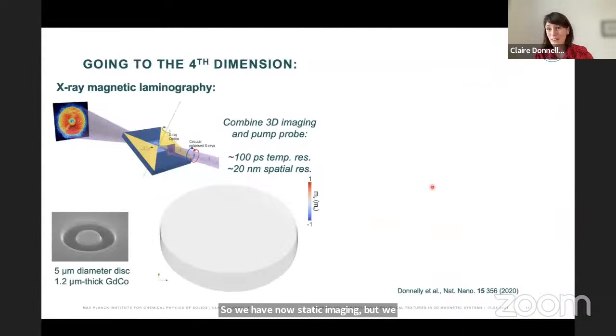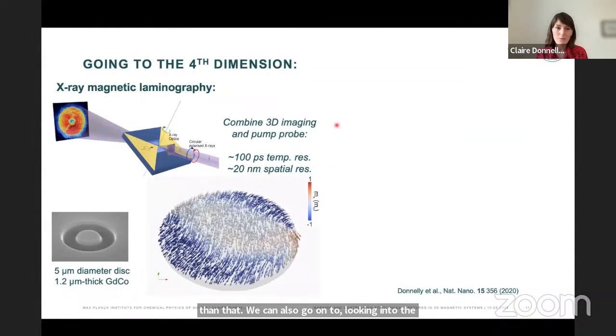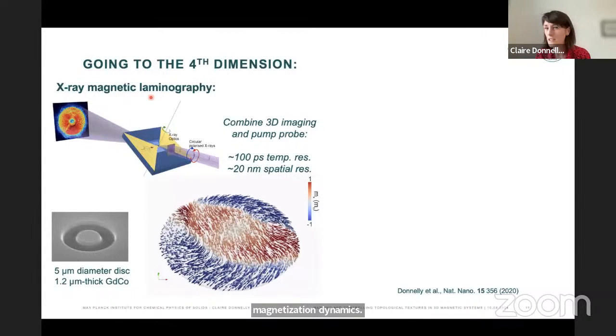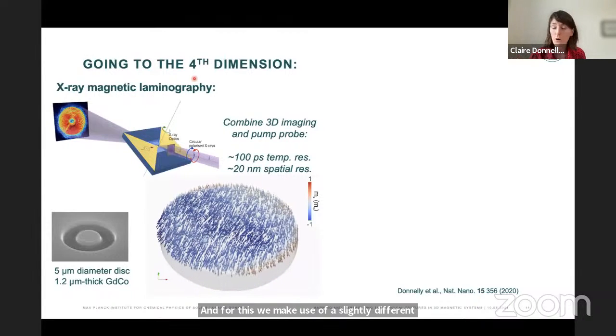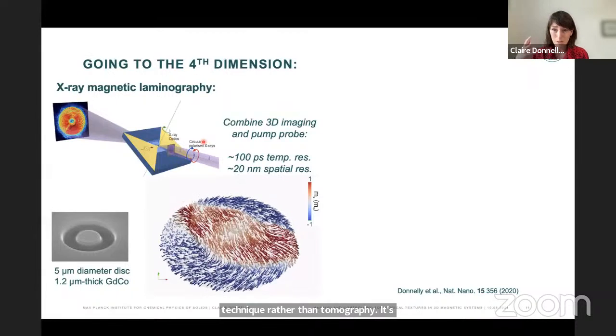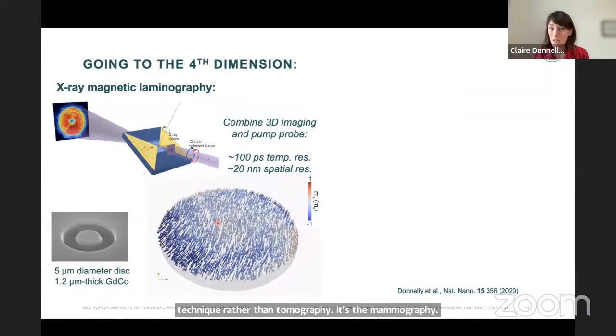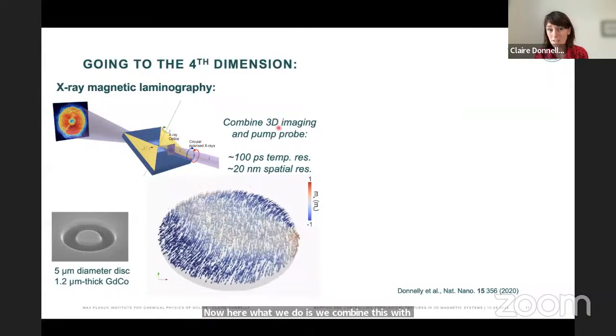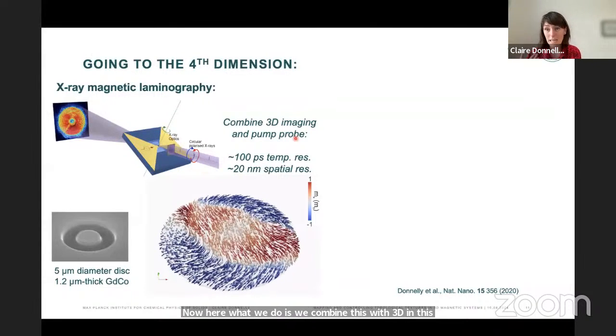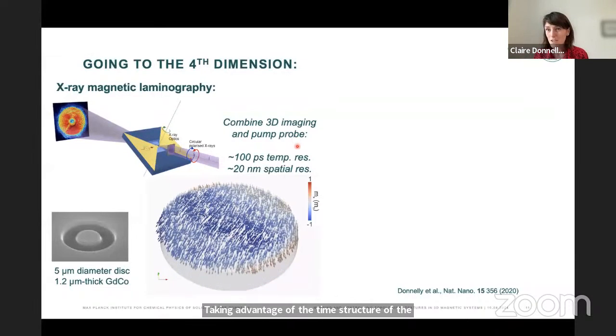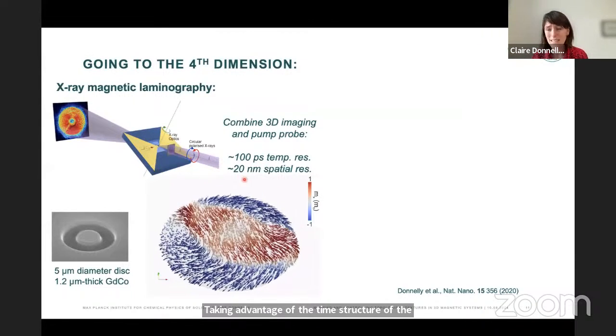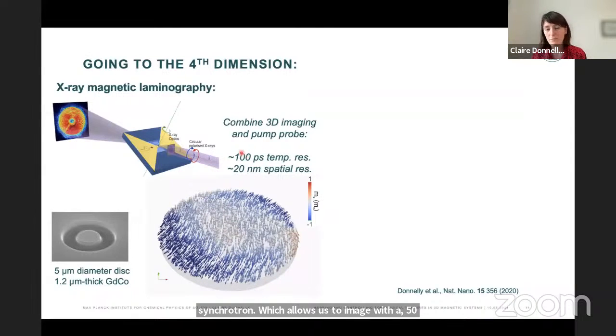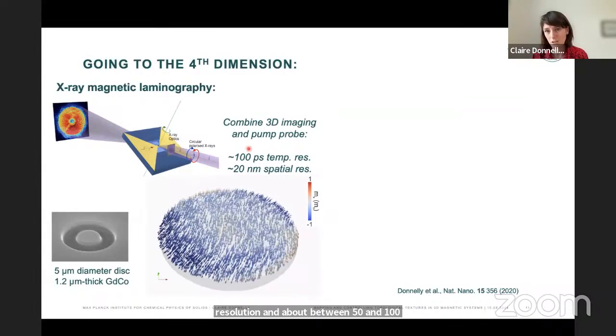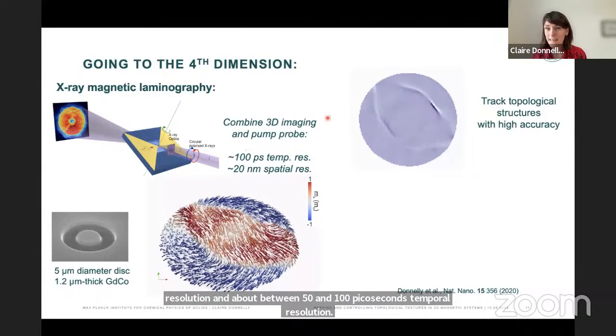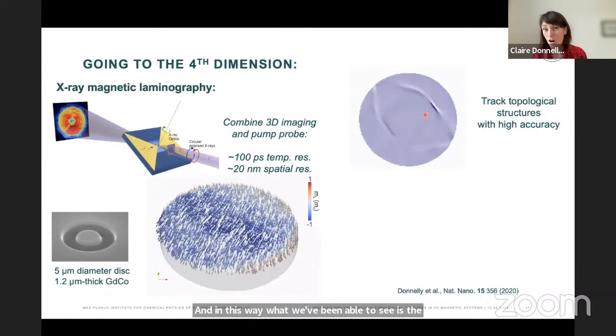We can also go on to looking into the fourth dimension where we can image three-dimensional magnetization dynamics. And for this, we make use of a slightly different technique. Rather than tomography, it's laminography. The same principle holds. It's a three-dimensional magnetic imaging technique, which we can also use for static imaging. Now here, what we do is we combine this with 3D imaging with a pump probe, taking advantage of the time structure of the synchrotron, which allows us to image with sub 50 nanometers, on the order of 20 nanometer spatial resolution, and about between 50 and 100 picoseconds temporal resolution. And in this way, what we've been able to see is the dynamics in 3D of topological textures.